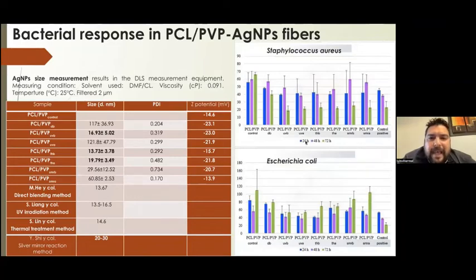In the case of the antimicrobial activity of these silver nanoparticles, we have these fibers with silver nanoparticles of 16 to 100 nanometers, so very, very small silver nanoparticle sizes. Compared to the literature, where they publish silver nanoparticles loaded into fibers with 13 nanometers and so on, we have good results in these experiments.